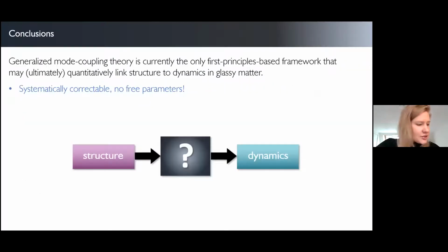And with that, I'd like to wrap up and conclude. So this framework that we call Generalized Mode-Coupling Theory, first put forward by Grzegorz Szamel in 2003, is now starting to emerge as a purely first principles based framework that has the potential to ultimately become quantitatively accurate, to link the very subtle changes in the structure of a glass-forming material to the emergence of glassy dynamics and this spectacular slowdown over many orders of magnitude. So it's systematically correctable.